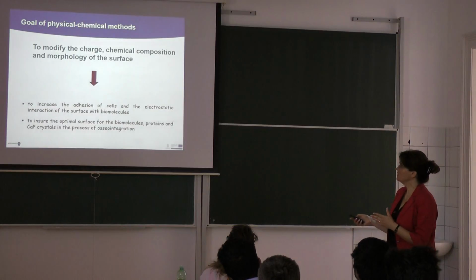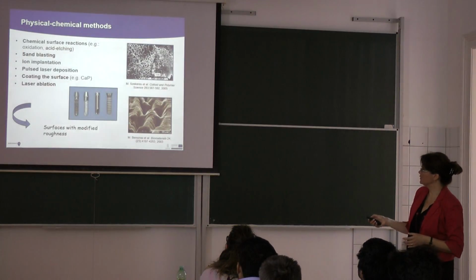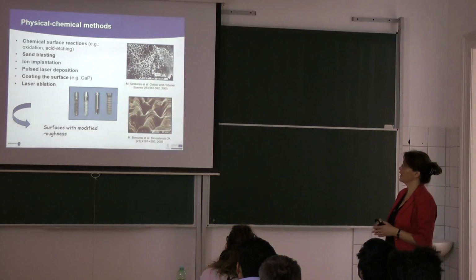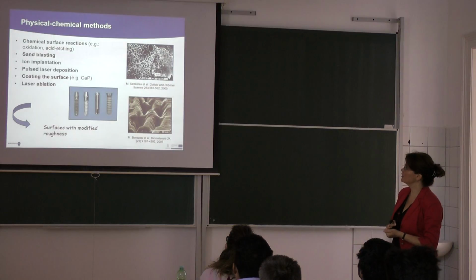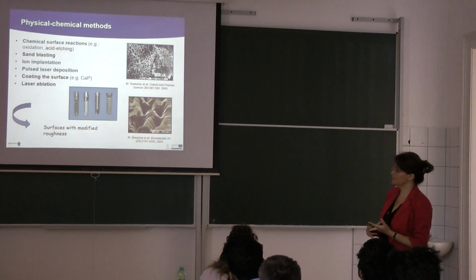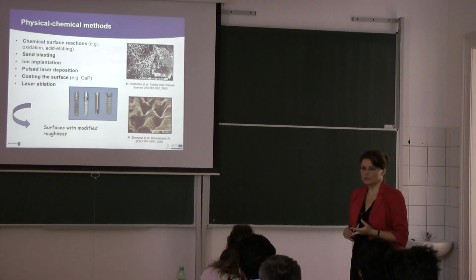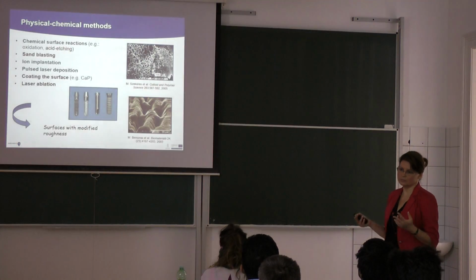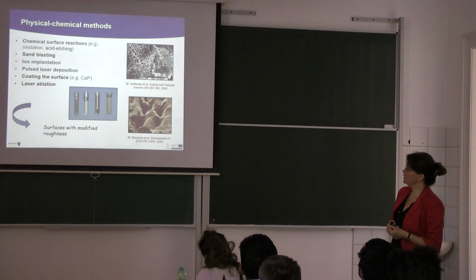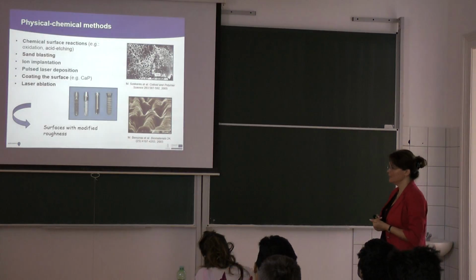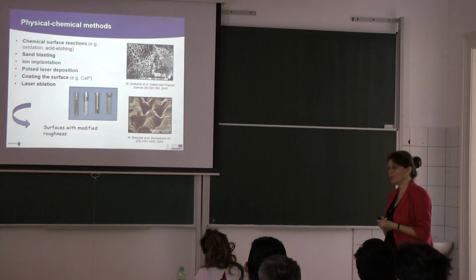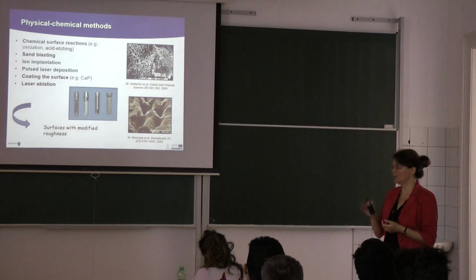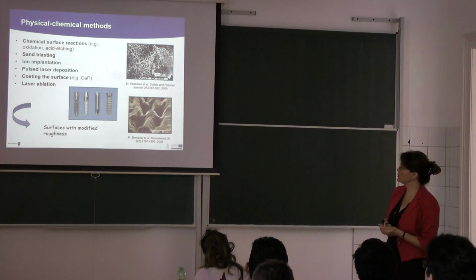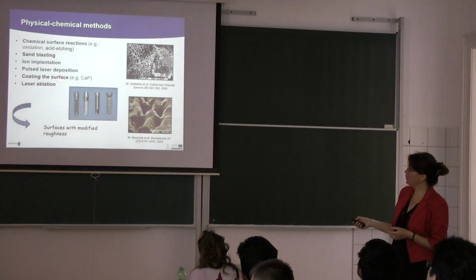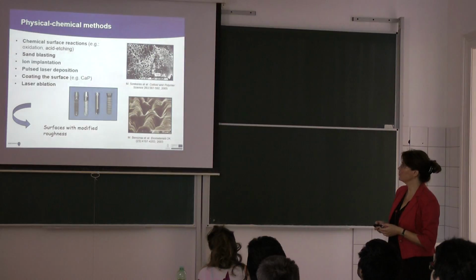But when you are doing a calcium phosphate coating, for example, you can see it here, then that is still a physical chemical method. So what kind of physical chemical methods? Chemical surface reactions, like for example oxidation and acid etching. The oxidation of titanium is also a chemical modification, yes? Then they very often use sandblasting. Ion implantation means that you are bombarding with nitrogen ions and you will have very good mechanical properties of those implants. Then you can use pulsed laser deposition. We also have some publications regarding that.